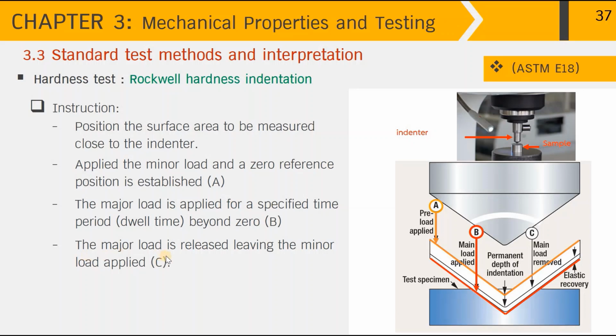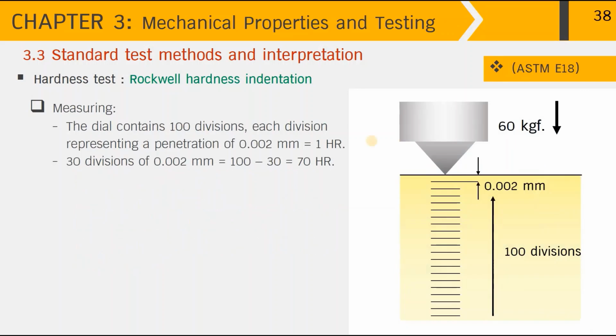And after that, the major load is released, having the minor load applied at C. And you can see that from B on the red line to C on the green line is the elastic recovery released by the metal surface that had been deformed in the first place. So the actual penetration height can be measured from A to C, as the value of Rockwell hardness is measured by the depth of penetration, as you can see from this picture.